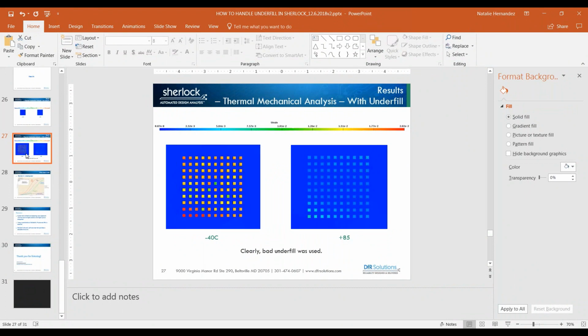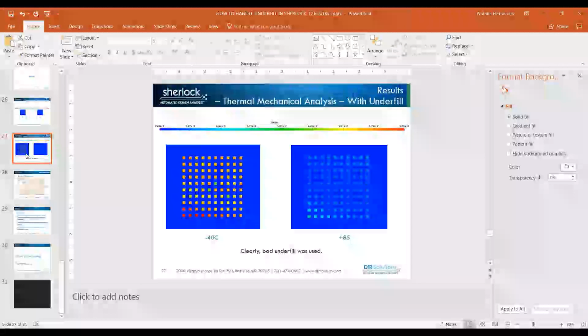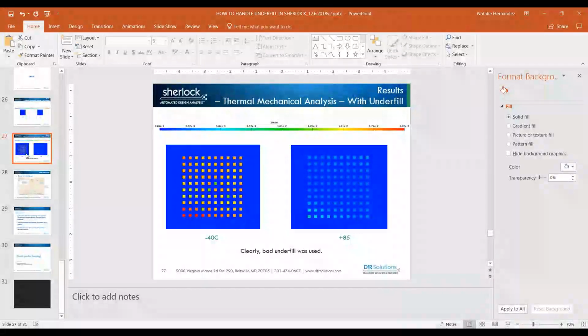in this specific example, because there was a bad underfill applied, you'll see that at the very low ends, there are very high strains happening. It's going to cause a bit of a compression of the solder joints. And then at the higher temperature, you'll have a bit of bouncing back, so to speak.